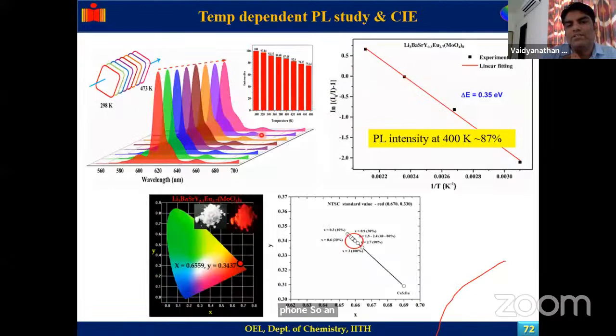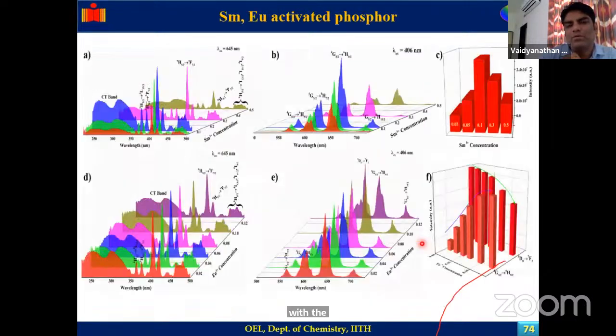And with the Arrhenius equation, when we increase the temperature from 100 degrees to 250 degrees, our compound is very stable. The CIE color coordinate shows it's a pure red color. We fabricated the LED by combining this, and we got red. When you combine with yellow, we get an improved emission. And when you combine with phytochrome R, we get an absorption here, and hence one can use this light for plant growth application.